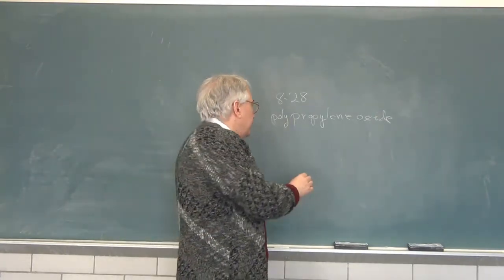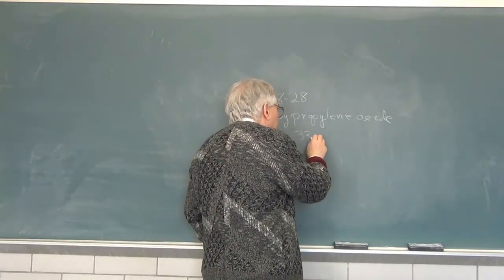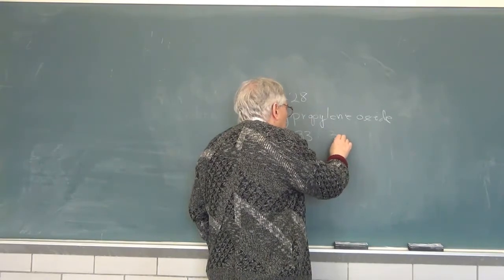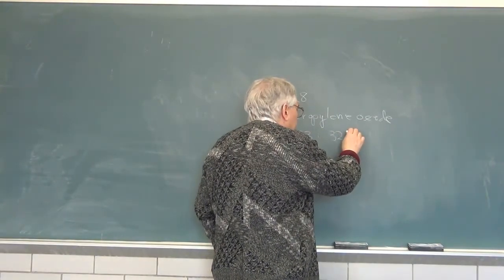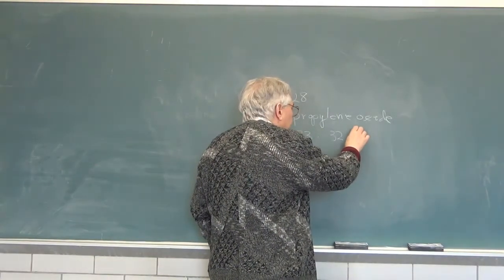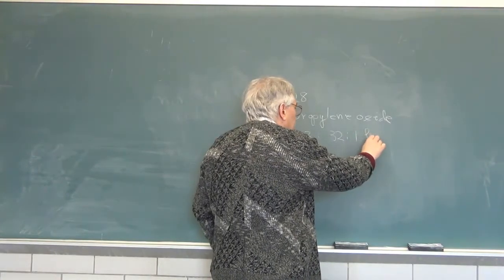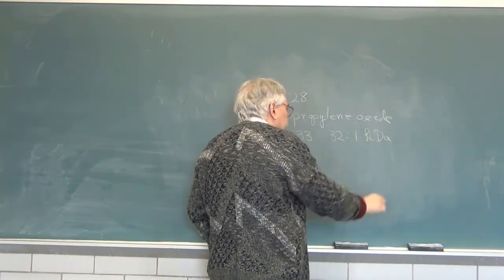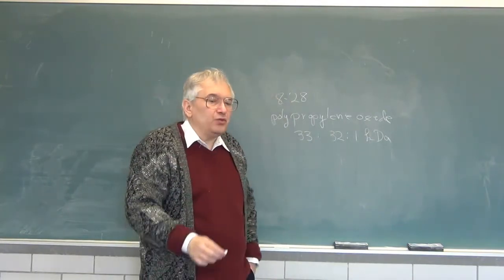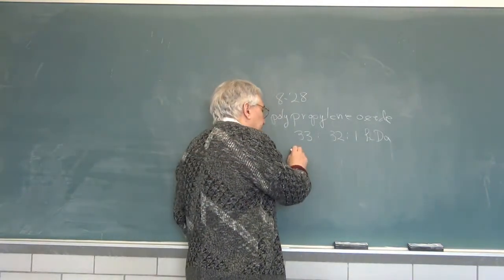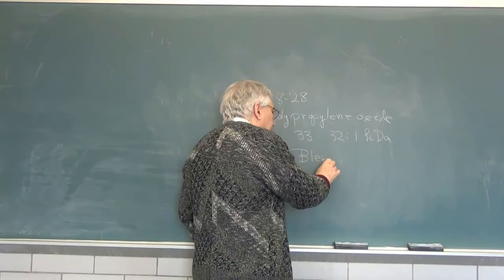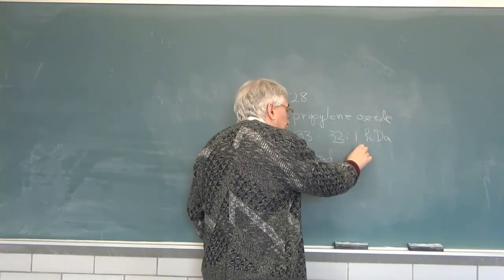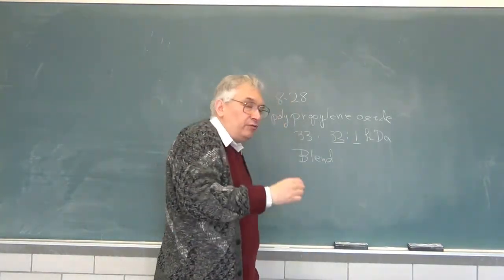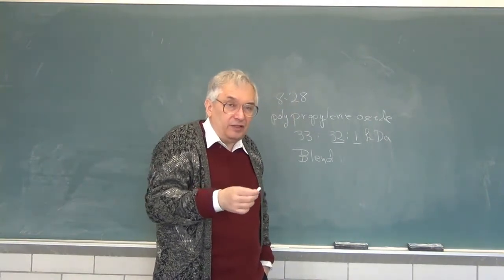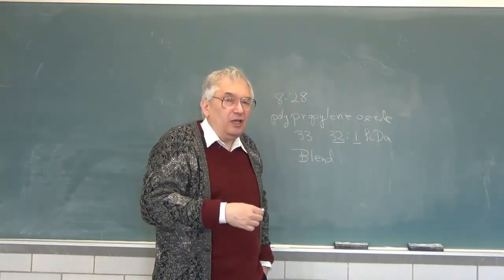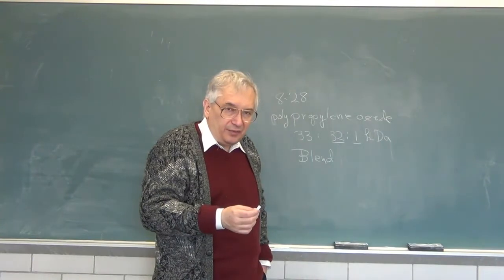Well, the first set of measurements is a 33 kilodalton probe in a 32 kilodalton matrix, except it's a mixture of 32 kilodalton and 1 kilodalton polymer. This is what is called a polymer blend. In a blend, you have, as you would expect, several molecular weights of, in this case, a given polymer. You've mixed them in combination.